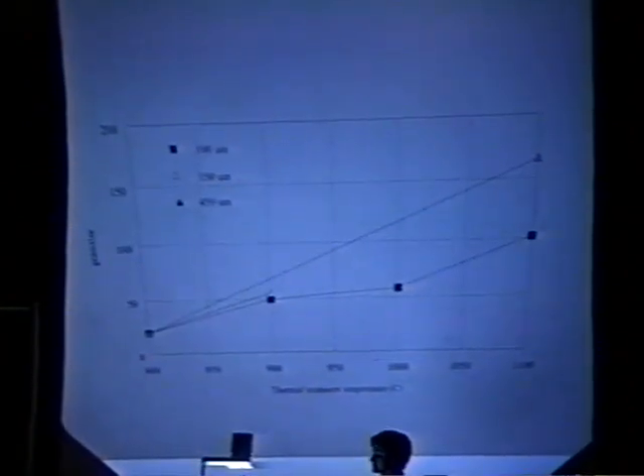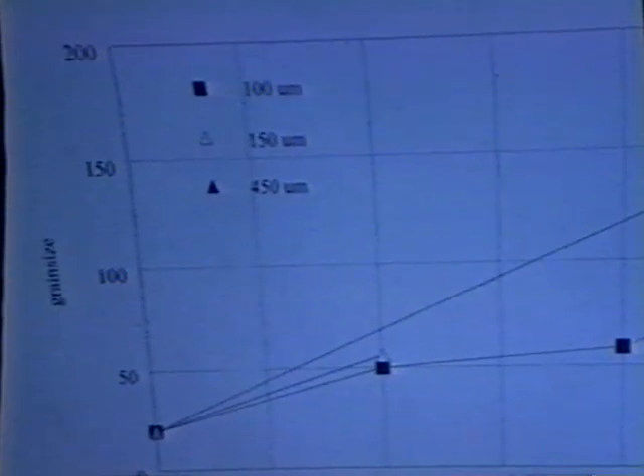We started from the same piece of palladium, then we cold worked it, reducing the thickness to different thicknesses, 100 microns, 150, 450 microns, so with different reduction rates. Then we annealed the samples to different temperatures, and we found that there is a maximum. Then we performed a scanning electron microscope analysis, and we correlated the grain size to the thermal treatment temperature. So there is a maximum loading ratio with respect to the grain size.